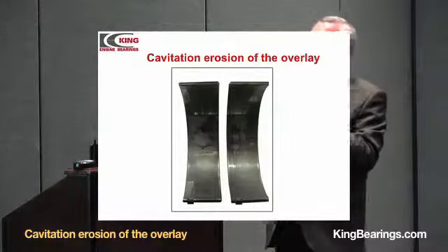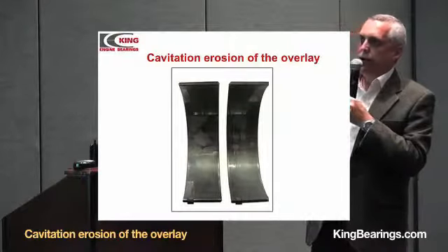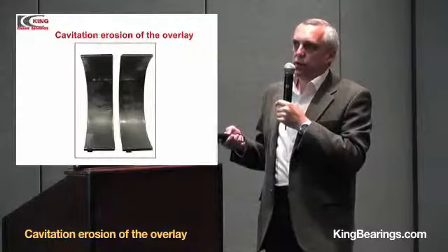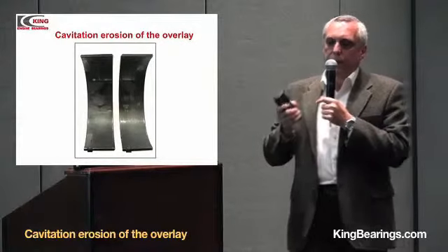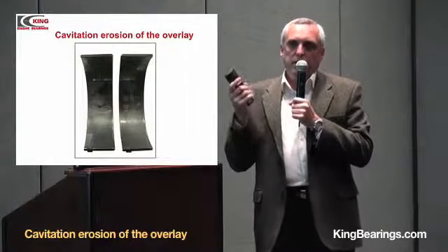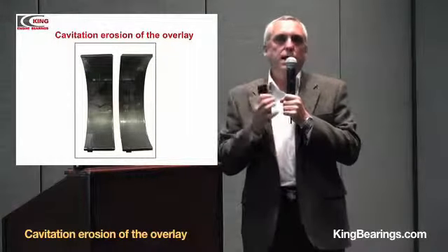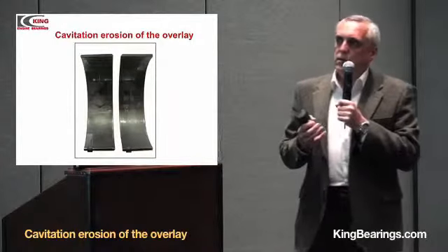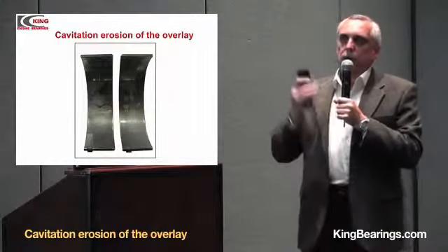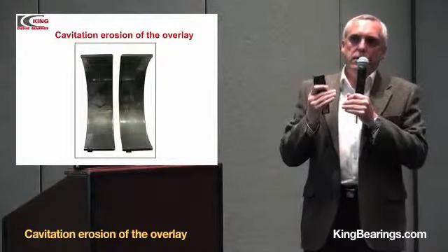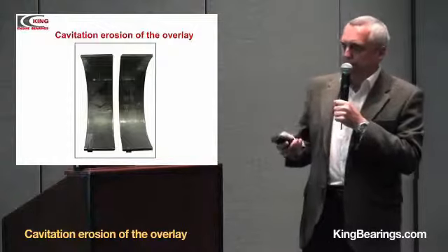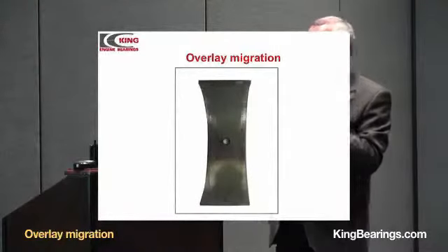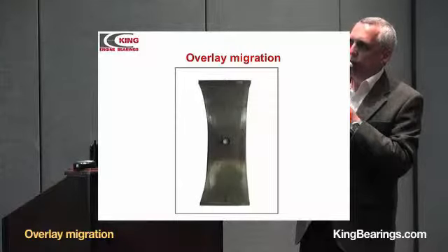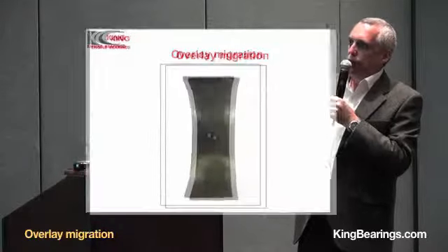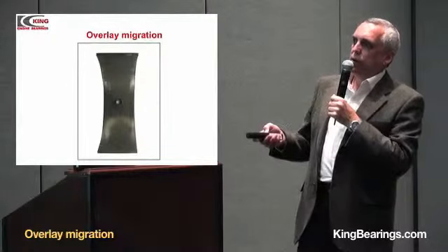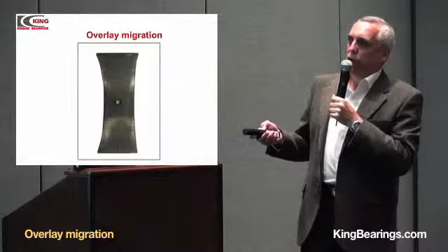And this is the cavitation erosion. These areas are eroded. Actually, there is no overlay here. It is gone by the erosion resulted from closing up of bubbles forming in the oil when the pressure changes very sharply. And this is overlay migration. You see parts of the overlay that was taken from one area and then stuck to the other area of the bearing.